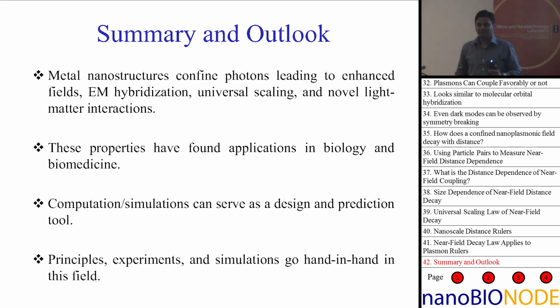Zero. No dipole moment. An excitation which has no dipole moment does not interact with light. It does not show up as any modes in the spectrum. That's why you did not see that mode, or that mode. Same way with the end-to-end, right? If the two dipoles are equal and opposite, they cancel out. Now, when you take a dissimilar structure, you break that symmetry.